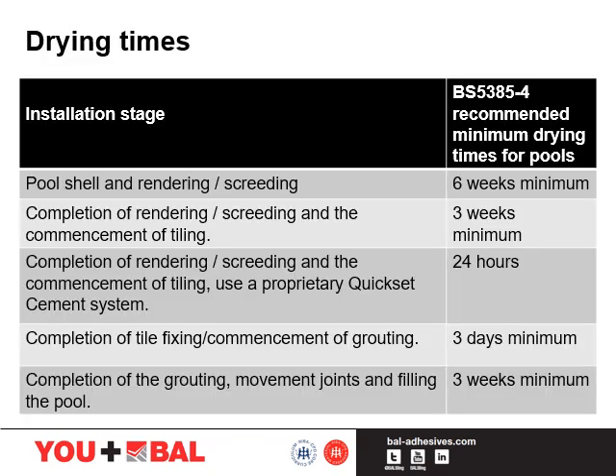On this slide we're showing you a table which details the drying times of constructional backgrounds when used in a pool tank. Normally, under no circumstances would we reduce these intervals. A longer period is sometimes necessary in wet weather or poor drying conditions, but by replacing Portland cement in screeds and renders for a rapid setting cement or a pre-blended product, we can reduce these, sometimes down to 2 hours for a render and 24 hours for a screed. It's always advisable to check with the manufacturer of those products prior to specifying them.